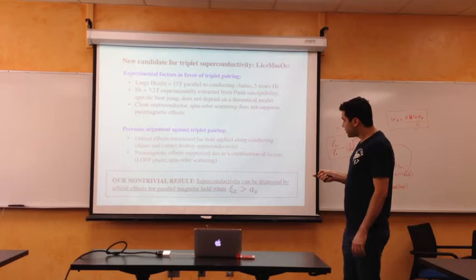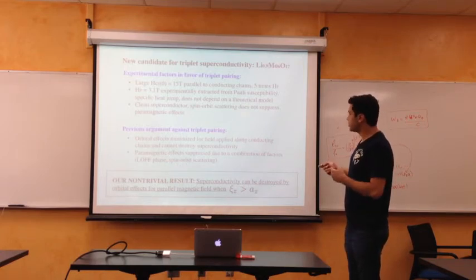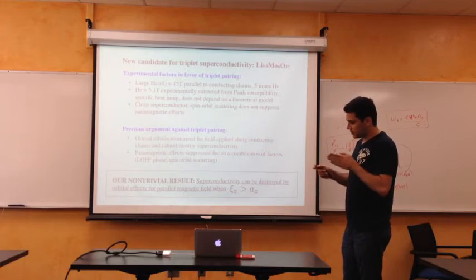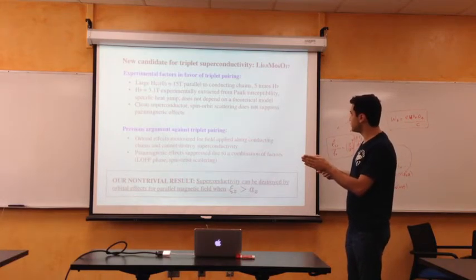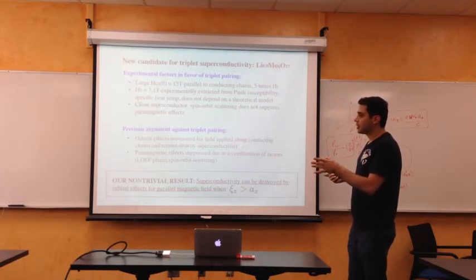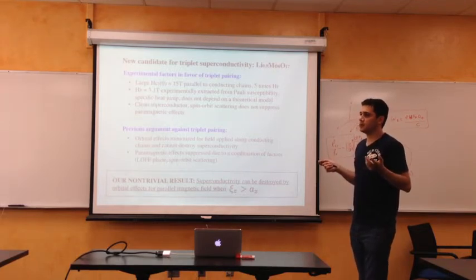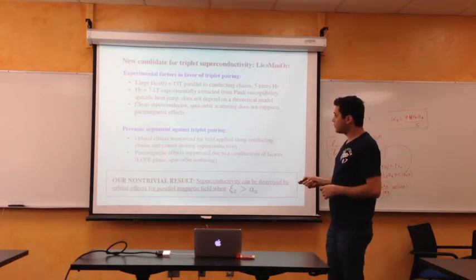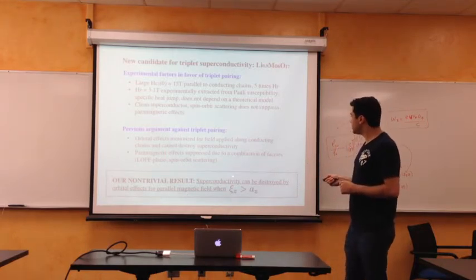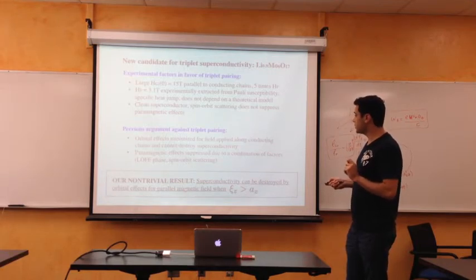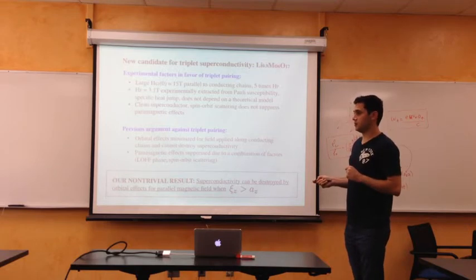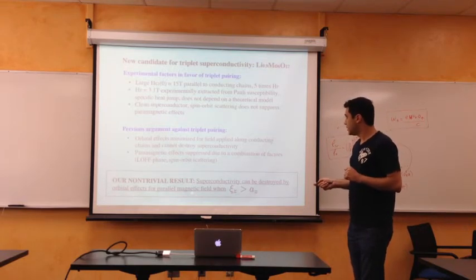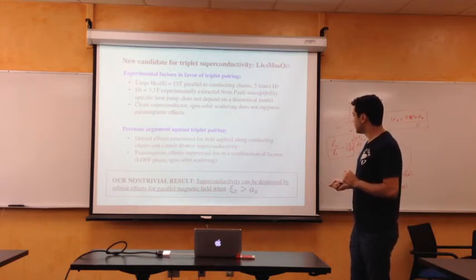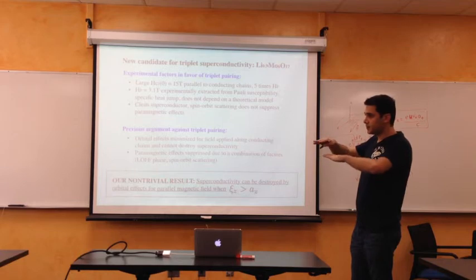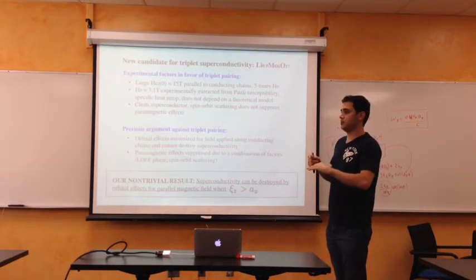So previous arguments against triplet pairing - and this is an important point - is that the field here is parallel to the most conducting axis, so the Lorentz force is minimized. So orbital effects are insufficient to destroy superconductivity, and therefore it could only come from paramagnetic spin splitting. Our non-trivial theoretical result is that superconductivity can in fact be destroyed by pure orbital effects, even when the magnetic field is parallel to the most conducting axis. One of the requirements in this case is that the conducting planes are well coupled.